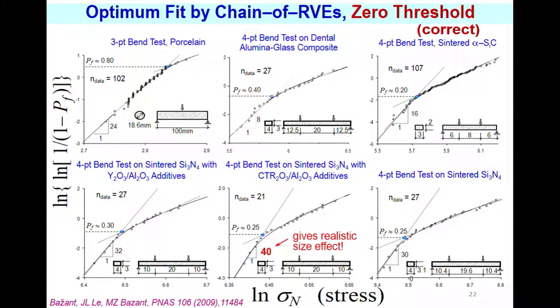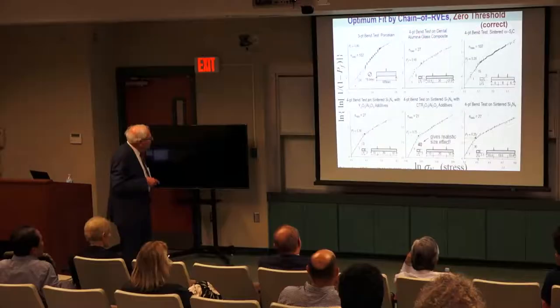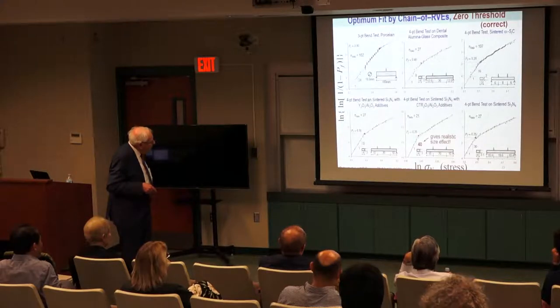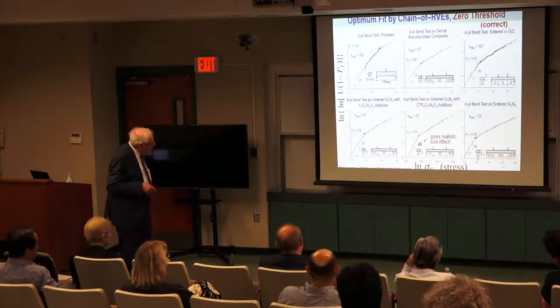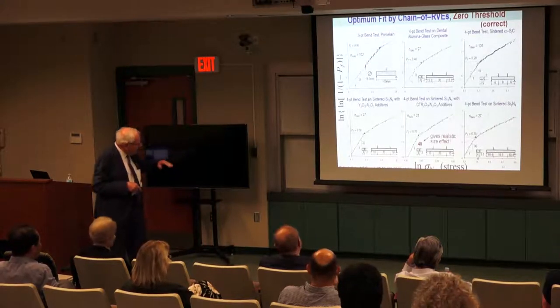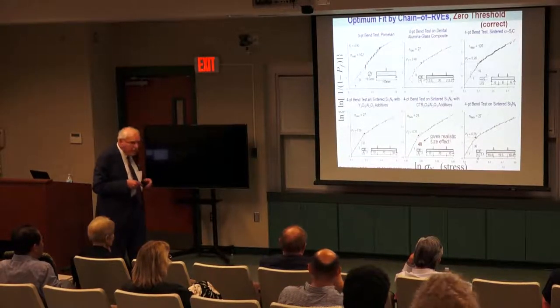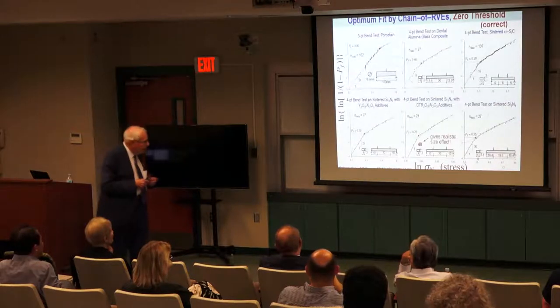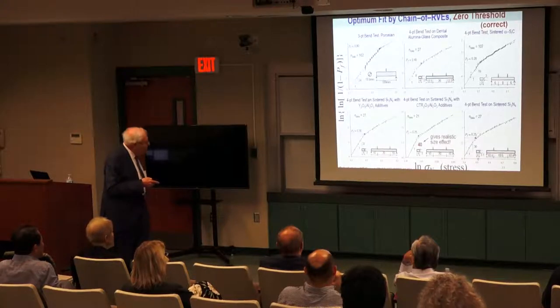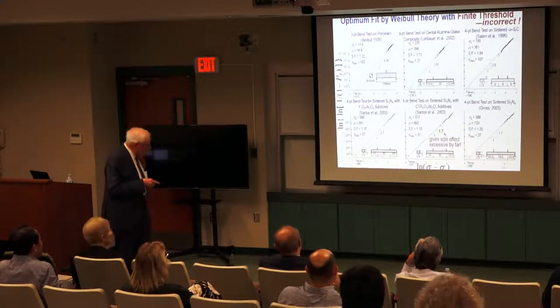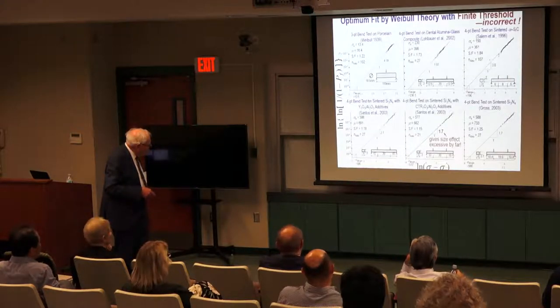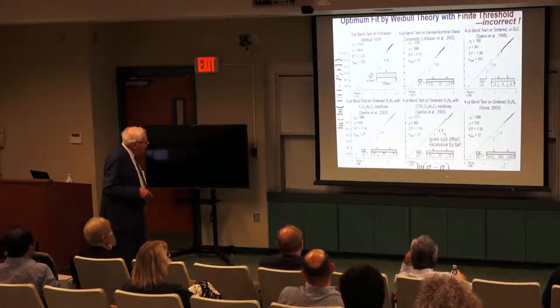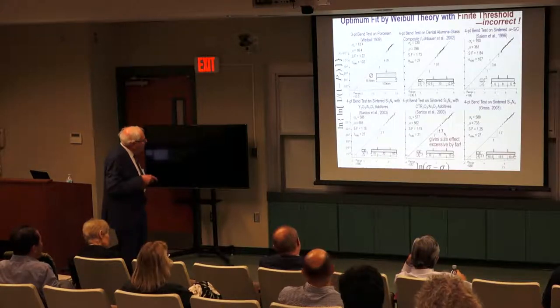Now these are some more recent papers on various ceramics, porcelain, dental composites, silicon carbide, silicon nitride, and so forth, taken from recent literature, and they all observe these deviations. If you plot it in Weibull scale against the total stress, you observe these curves. It is interesting to note that the exponents of the Weibull part are high, like 40. The size effect in the mean is actually 1 over this exponent, so the size exponent would be 1 over 40, very small. And indeed, the size effect is very small in these materials. But what they do is fit it by a distribution with a threshold. I'm sorry, this somehow cuts the bottom of every slide. There's sigma U, the threshold, here.